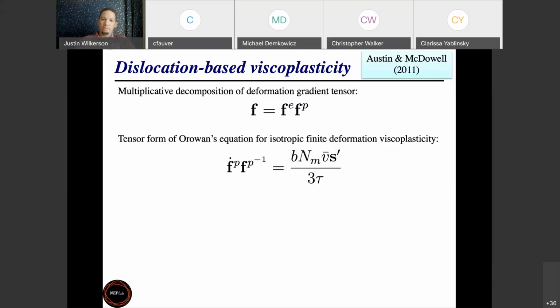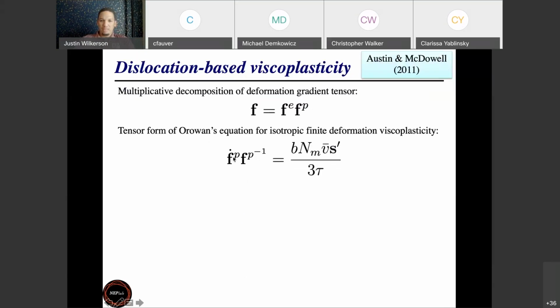And so for that, we make use of this dislocation-based viscoplasticity model of Austin and McDowell. It has a multiplicative decomposition of the deformation gradient tensor into an elastic and a plastic component. The rate of plastic deformation is given by the tensorial form of Orowan's equation. On the right-hand side, I have b representing the Burgers vector, N_m being the mobile dislocation density, so the density of mobile dislocations in the material, and then v being the average dislocation velocity in the material. S prime here is the deviatoric stress tensor, and then it's just normalized by a scalar von Mises stress.